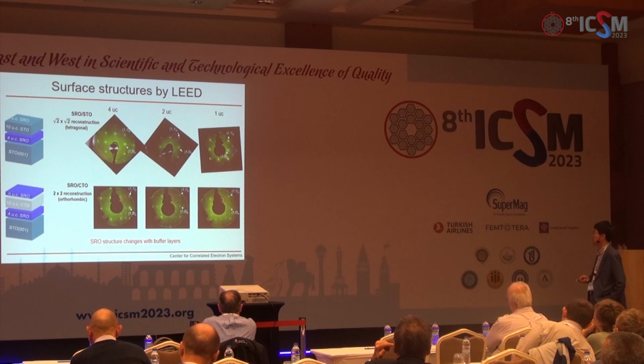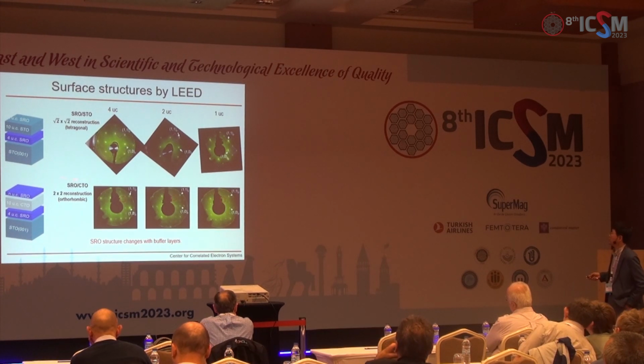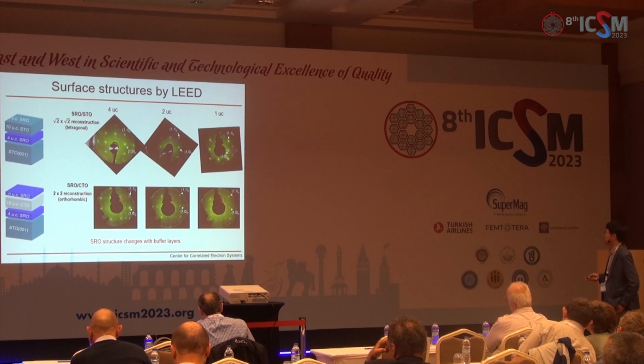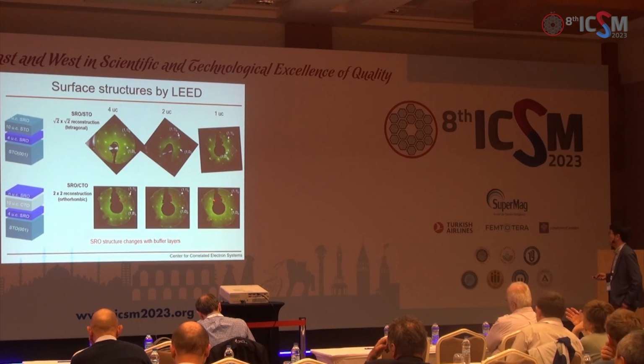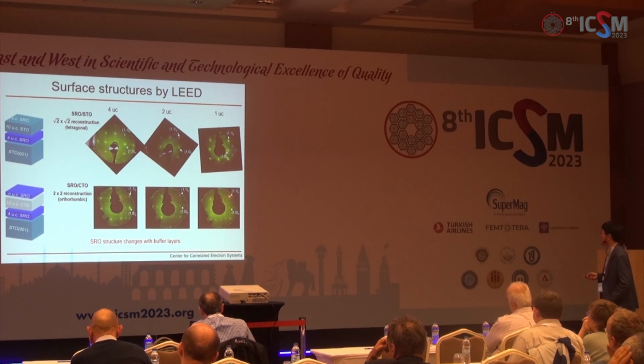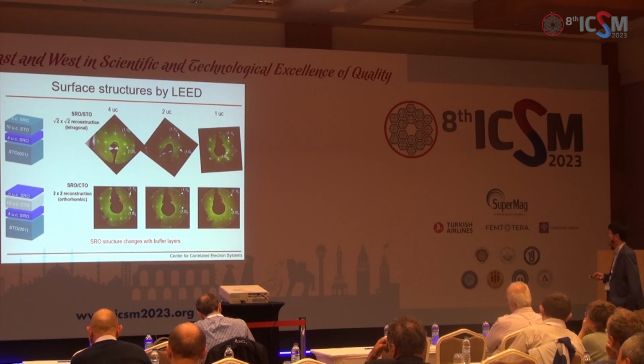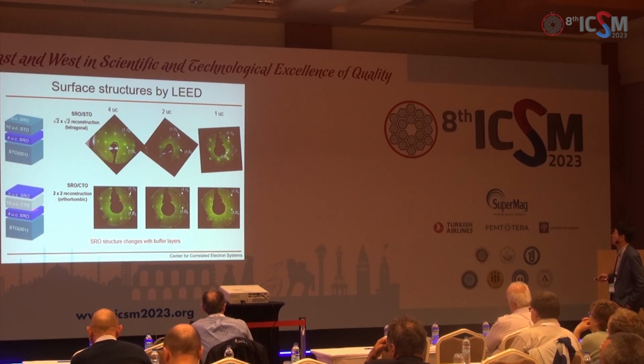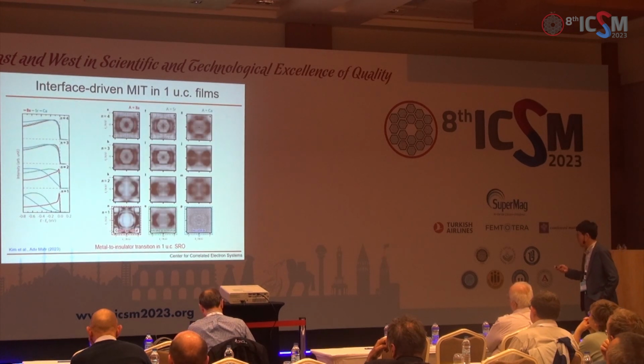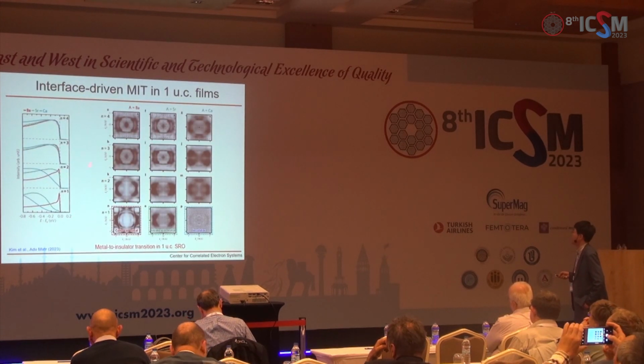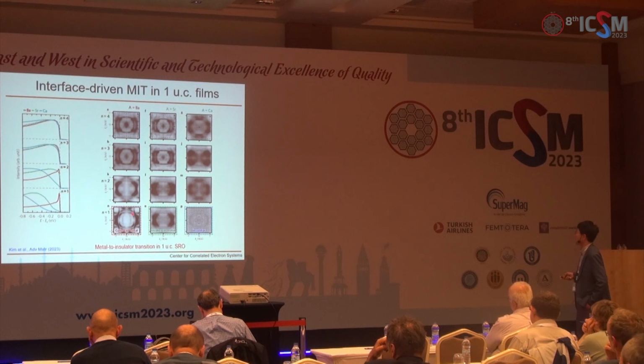That means it's in tetragonal structure with rotation only. Meanwhile, if we grow strontium ruthenate on CTO, we have 2 by 2 reconstruction. That means we have both rotation and tilting, and the unit cell is even smaller. So the strontium ruthenate one unit cell structure changes with this buffer layer, CTO or STO. And as we change the number of layers and substrate, the electron structure changes drastically.